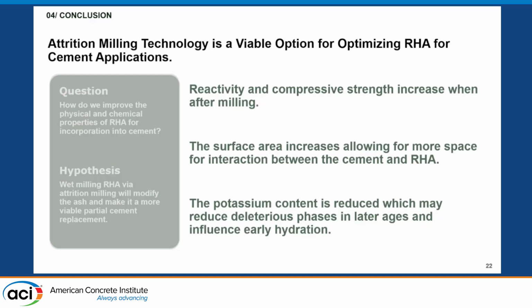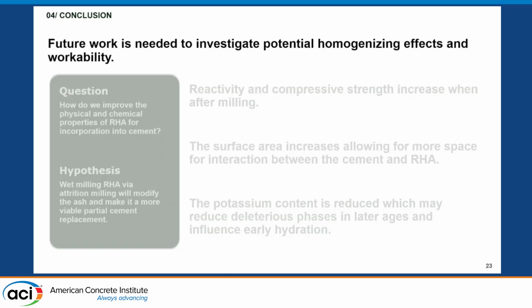And so some of these key conclusions is that the reactivity does increase after this milling process, so does the surface area, and the potassium content is reduced, which can potentially reduce unwanted phases in later ages, which I'm currently waiting for those cubes for, but can also influence early hydration as shown in previous works. Something that I am looking at more is kind of that homogenizing effect potentially from other rice hulls, but also looking at the workability of the material and kind of getting a more quantitative conclusion on that because it is definitely substantially more workable after that milling process.